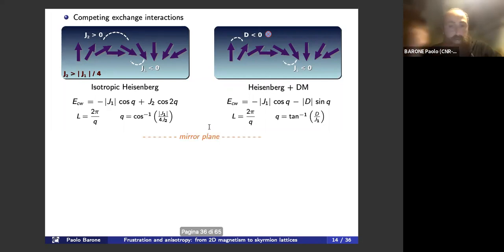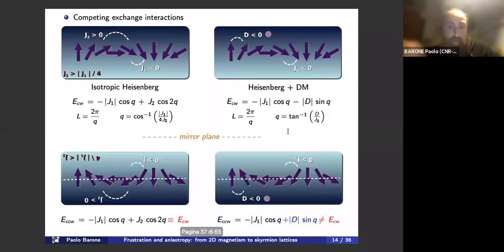So if we now assume to apply a reflection across a mirror plane, which is perpendicular to the screen and parallel to this line, we would end up with two spirals with the opposite handedness. So in this upper case, spins are rotating clockwise, and in these lower panels, they're rotating counterclockwise. Now, for the case of competing isotropic interactions, these two magnetic spirals are completely degenerate in energy, whereas these two are not, because the presence of the Dzyaloshinskii-Moriya interaction removes the chiral degeneracy, and this is why it is called a chiral interaction.